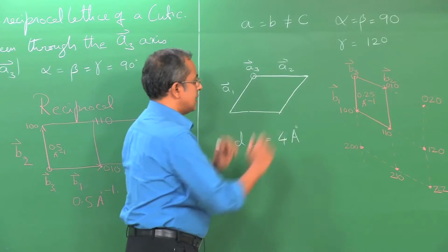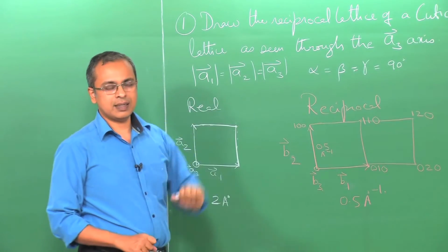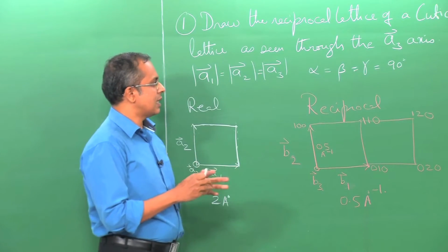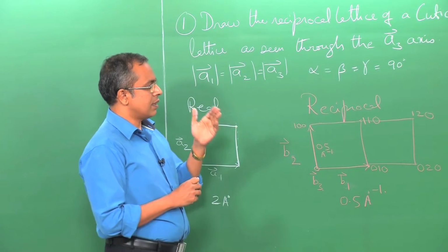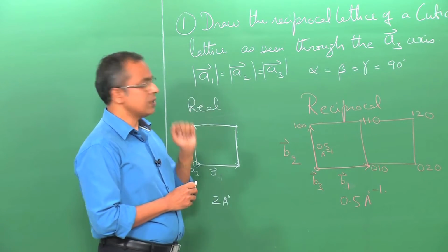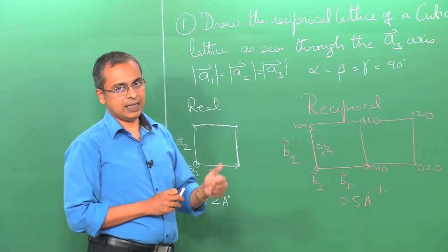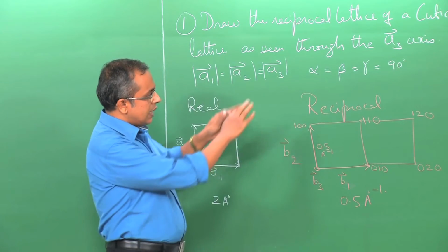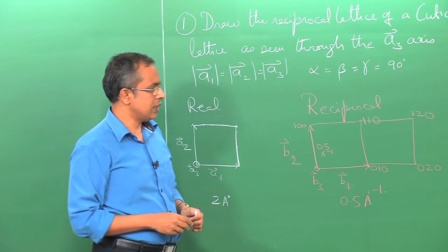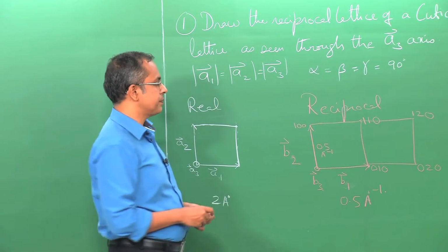So you see between this example and the example we did here, which is a cubic cell, and there you have done a hexagonal cell, we see that the two rules that we had, which is that the HKL is perpendicular to the plane HKL, and the modulus of HKL is 1 over the spacing of DHKL. So given those two rules, the geometry and layout of the lattice we have been able to show here in these two worked examples, and in principle you can extend this, right.